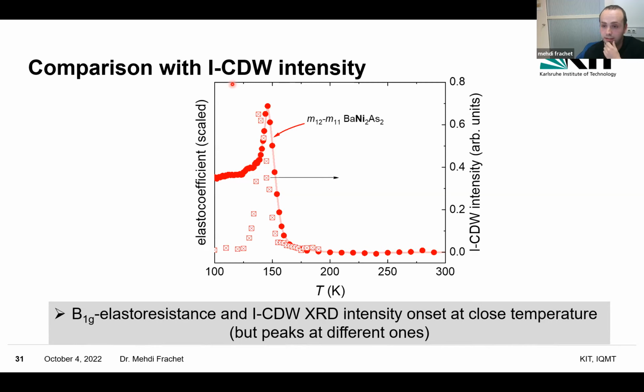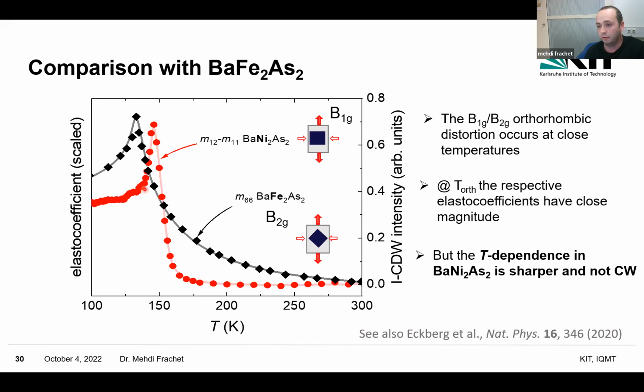But what we checked is that we measure upon cooling and warming to be sure that there is no hysteresis. We don't see any hysteretic behavior. And especially if you measure upon warming, the temperature difference between the triclinic phase and the orthorhombic phase is even smaller. I'm shocked that there is not a dramatic feature at the triclinic distortion. If you really look deeply, you see a small feature, but not that much. I will show the phosphorus doped compound afterwards, and in the doped compound you can see more features at the triclinic transition, which is far away from the orthorhombic one.